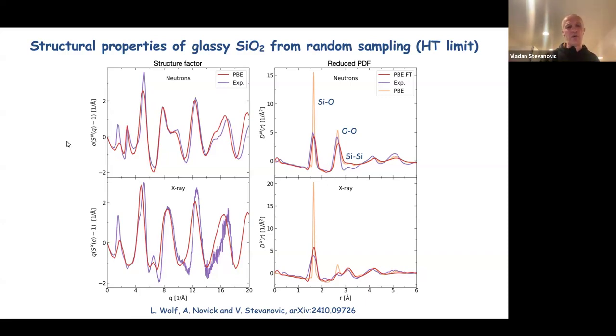Another thing is that this first peak in experiment is usually related in the literature to larger voids of radius of about 10 angstroms or larger that could be present in SiO2 as a consequence of the glass transition, that we just don't reproduce that well with 24 atoms. But other than that first peak, everything else is, at least to my taste, reproduced fairly well. Another interesting use case for this method is calculating properties of glasses without having to deal with large supercells.